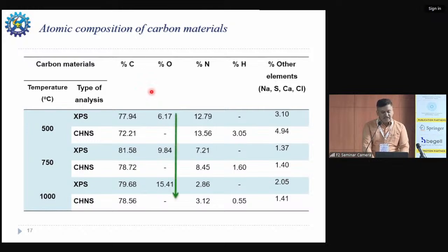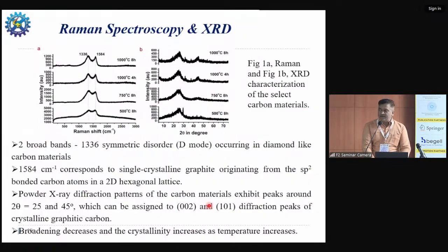When we look at the amount of oxygen and nitrogen, we can see that the oxygen is increasing as you increase the temperature, whereas the nitrogen is decreasing at high temperature. But still, there is about 3% nitrogen available, even in carbon prepared at 1000 degrees Celsius. These are the typical data related to Raman and XRD. We can see the typical D and G bands in the Raman spectroscopy, and the XRD shows the typical 002 and 101 diffraction peaks of the crystalline graphitic carbon material.